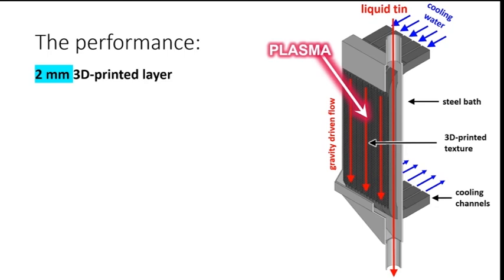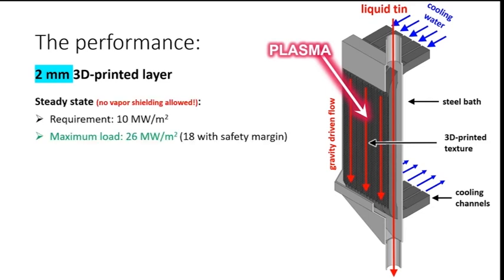So let's assess the performance for 2 thicknesses. I will start with 2 millimeters and then increase to a 3 millimeter thick printed layer. So in the steady state, remember, in steady state there's actually no vapor shielding allowed, because if we have too much evaporation, we contaminate the plasma. We are required to dissipate about 10 megawatt per square meter. And it seems in this case we can do it. While keeping below our evaporation limit, which is in fact the surface temperature limit, we can dissipate about 26 megawatt per square meter. If you put a safety margin on that, there is still 18 left. So this is very good.